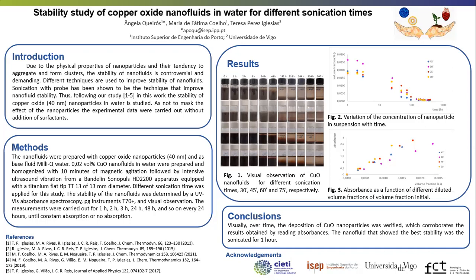As conclusions, visually, over time the deposition of CuO nanoparticles was verified, which corroborates the results obtained by reading the absorbance. The nanofluid that showed the best stability was sonicated for 1 hour.